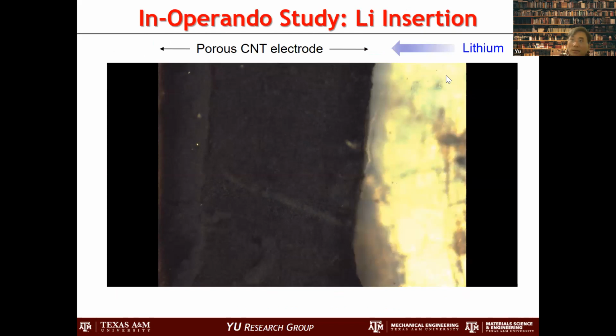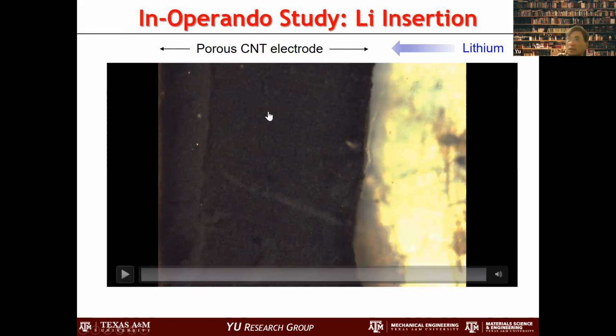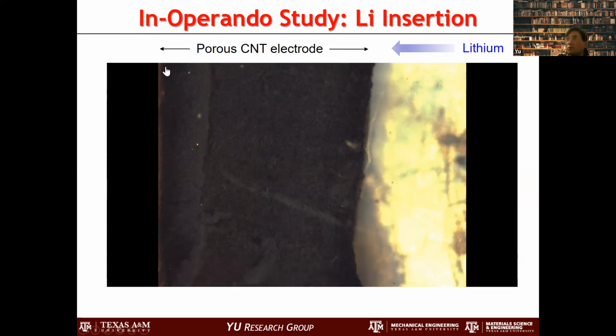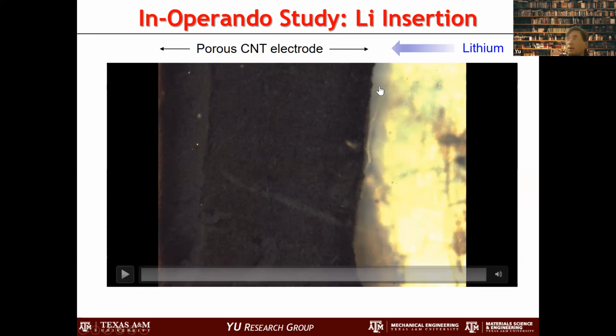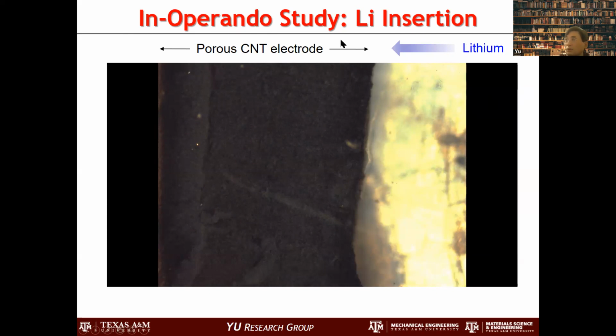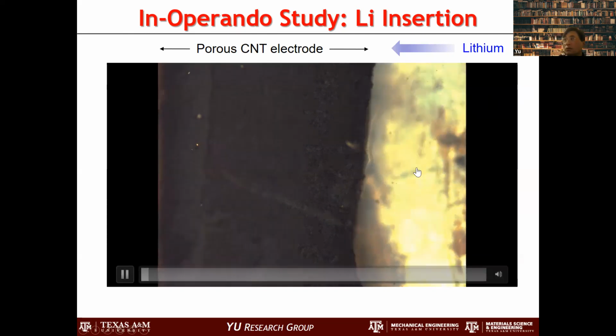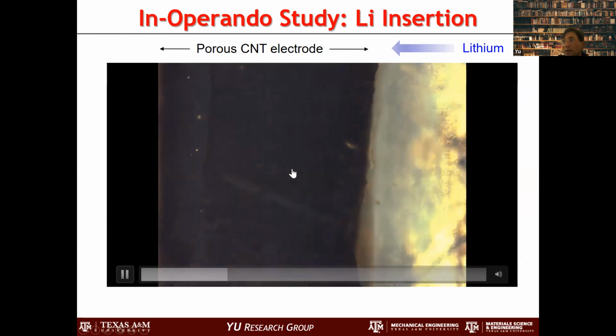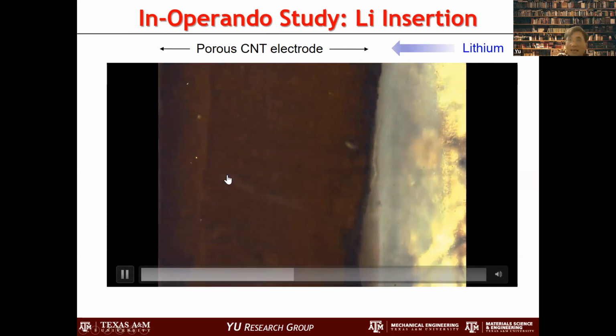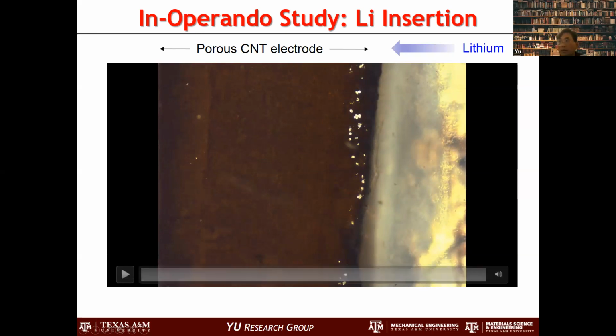So this is another video that we actually, not only we developed these devices, and actually we study what's going on inside. And this is an in operando study, which means that while we are operating the cell, we visualize what's going on. So this is our carbon nanotube electrode, functionalized carbon nanotube electrode. This is the lithium side. We're trying to infiltrate lithium, and when we infiltrate lithium, it becomes lithiated and becomes brownish color, which indicates that lithium is getting in, and getting in like this way. So this is what's happening. And so we visualize what's going on as well. And so we make sure that things are getting in, and so that we can make our device.